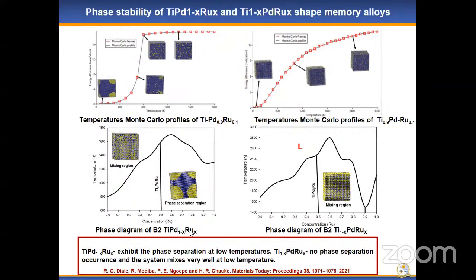This has been done for two different compositions, where the first one on the left here was the substitution on the palladium, meaning we were reducing palladium by adding ruthenium, while on the other side we are reducing titanium by adding ruthenium. So you get different kinds of compositions, which are very critical for the applications, because these are shape memory alloys that we're designing, titanium, palladium, ruthenium shape memory alloys actually, and these are considered high temperature shape memory. And as you can see, the temperatures are very, very high.